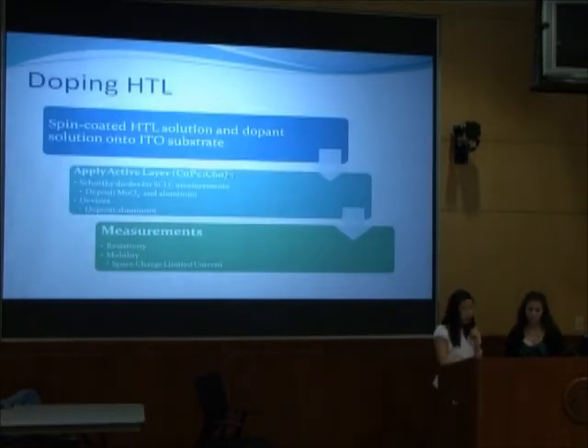Our next step was to incorporate the carbon nanotube anodes into a solar cell device with a doped hole transport layer. As you can see on the slide, this was our process for making those solar cells. We made both actual solar cell devices, and we also made diodes for the space charge limited current measurements, which tells us about the mobility of the device.